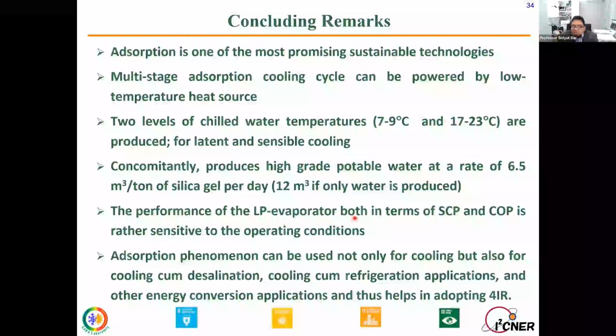The performance of the low pressure evaporator, both in terms of specific cooling capacity and COP, is rather sensitive to the operating conditions. Adsorption phenomena can be used not only for cooling but also for cooling cum desalination, which I already introduced. Also cooling cum refrigeration if you use alcohols, and other energy conversion applications, and thus helps in adopting 4IR, even now 5IR. And here I put 4 small symbols. This is SDG 6, which is clean water and sanitation, and then SDG 7, which is for clean energy, and then SDG 11, and also SDG 13, which is climate action. So we can contribute to all these 4 SDGs.